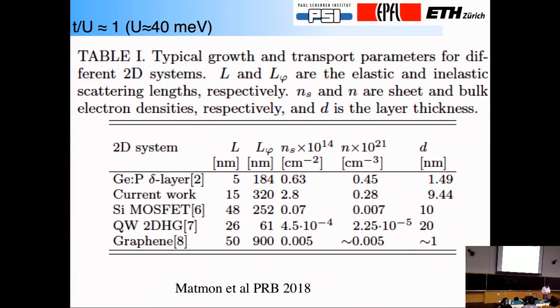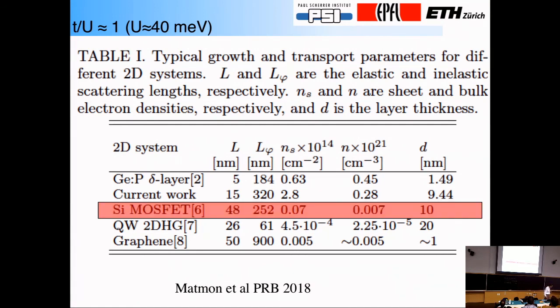We haven't actually implemented that yet for the ordered Hubbard model, but we have certainly started doing experiments where we've looked at disordered two-dimensional physics, the disordered two-dimensional Hubbard model, and in particular what we've already done and we've published is actually a look at the disordered 2D system and at a density which is much higher than what has been achieved with silicon MOSFETs. So this just shows a table. I'm not going to go through the details, but the point is that we can actually go into a regime where our carrier density per square centimeter is 2.8 times 10 to the 14th rather than 0.07, which was sort of the largest that was achieved in the MOSFETs.